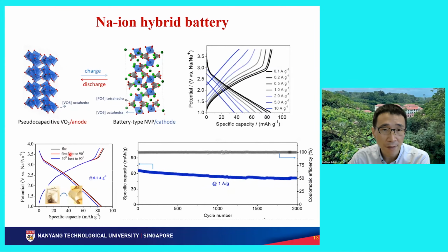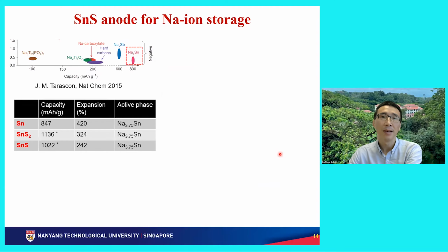So it can bend, it can flat bend 90 degrees or bend many times, and the charge-discharge curve doesn't change much. It can also run at 1 ampere per gram, which is a high current, up to 2,000 cycles. Of course, it can also run at low currents, but low current takes a longer time to test, maybe more than 3 months. Okay. So this is the cathode one, or this is the full battery one.